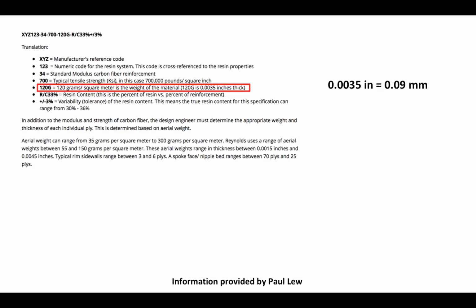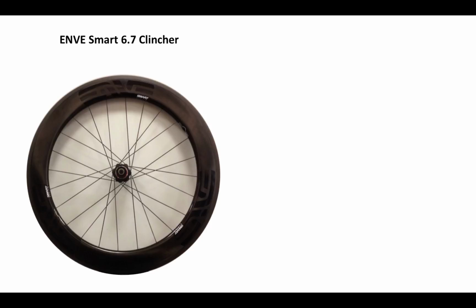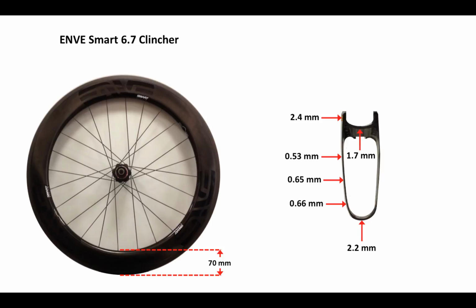Here's my first arc-shaped piece, in this case without showing all of the individual fibers. This is what my wheel would look like after putting on three more shapes of arc exactly the same. But one layer of prepreg does not constitute my rim. From this information here, I can see that my ply is only about a tenth of a millimeter thick. But using this ENVE rim as an example, the depth of my rim is 70 millimeters. But in the sidewall, you see that my rim is somewhere around a half a millimeter thick, meaning I can have perhaps five or six plies of prepreg.